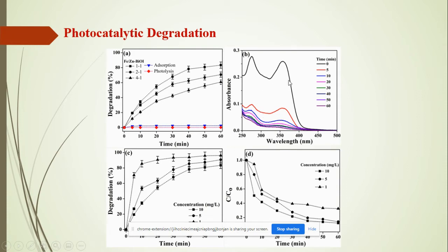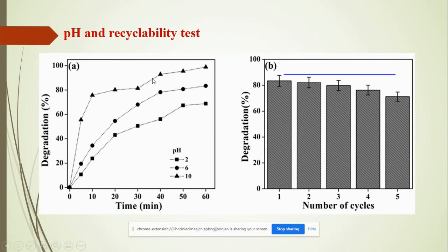Here you can see the UV visible spectra, from where the percentage degradation is calculated, as the peak decreases with time. We also checked the pH and recyclability of the material. Basic conditions are the best conditions for the degradation of tetracycline, and almost 96% degradation was found at 10 ppm of concentration. While using acidic conditions, the degradation decreased and reached up to 60%.